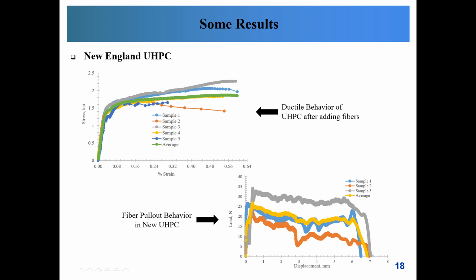Preliminary results obtained by the direct tensile tests and the single fiber pull-out tests are shown here. Both results are very promising. The direct tensile tests show great consistency, strain hardening behavior, a tensile strength of up to 2 ksi, and ductile behavior indicated by a peak strain of more than 0.5%. The pull-out results show high load resistance and shear strength hardening. This is seen by keeping the pull-out load almost constant, although the fiber is being pulled out and thus steadily reducing its embedded length. More tests will come.